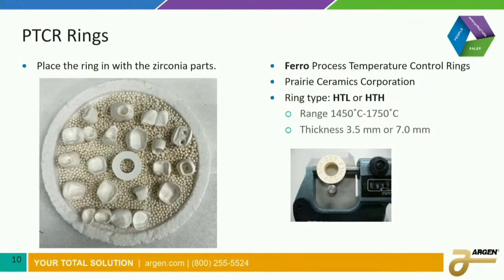Now, how do these things work? Well, these things come when you buy them, and you could buy them at Prairie Ceramics or Zon or a number of places. When you buy them, they come with a little sheet. For that lot of material, it correlates the temperature with the size of the disc. So as the temperature goes up, this disc will shrink, and the amount it shrinks at the end determines the maximum temperature that it saw. And that's the temperature of your furnace.